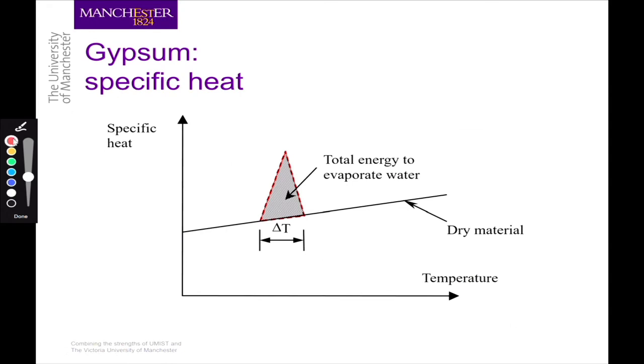The first aspect is dealt with by specific heat. For example, if this is the specific heat as a function of temperature of the dry material, that's gypsum. But gypsum has a lot of water inside. In order for water to evaporate, water will become steam. That requires energy, and that takes energy away. What we normally do is convert this process into some sort of equivalent additional energy in the specific heat of the material. But of course, this additional heat depends on how water moves around. So really, we have to carry out combined mass transfer, which is water movement, and heat transfer, which we did, and then we found out how to increase this value depending on different fire conditions.